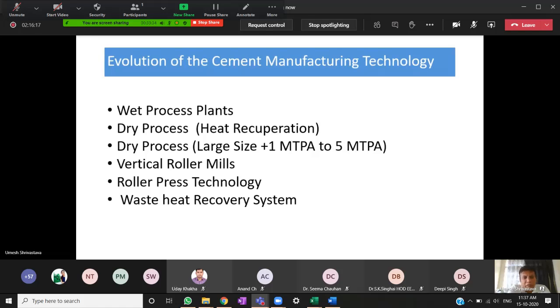All the wet process plants are totally closed, and running a wet process plant means you are using at least double the coal, double the quantity of coal that you are using now, because you have to make the moisture which you have added from grinding evaporate. After that, the dry process technology came, where there is heat recuperation, and I will take you through those aspects also. Dry process plants were up to 1 million ton plants. So that was a transition of technology from wet to dry.